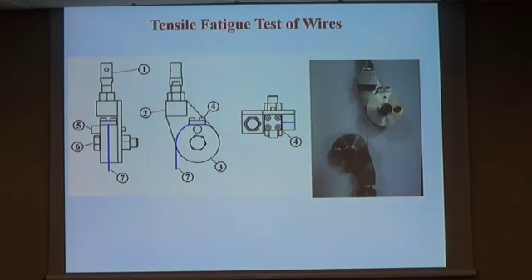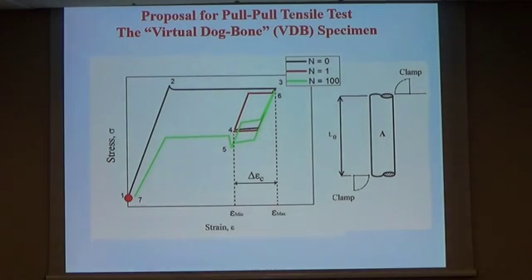When we're dealing with thin wires in tension, we need to use this kind of device because we cannot get a geometric dog bone shaped specimen, mainly when we also want to analyze the surface condition of the wire. But we have an extra problem with this kind of material: the martensite transformations usually take place in the clamp. So the idea was to propose what we call a virtual dog bone specimen.